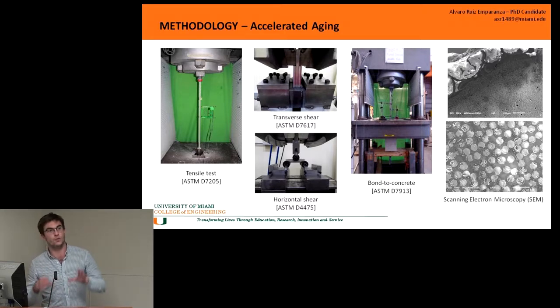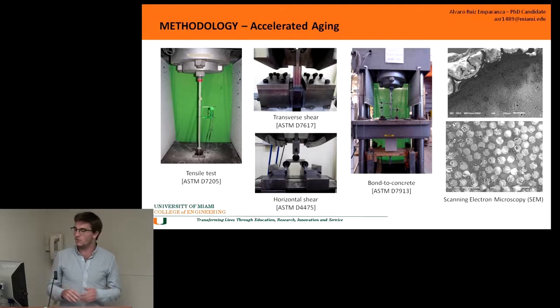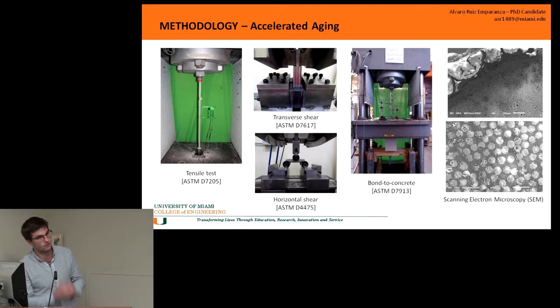So what we need is to check the properties before and after this accelerated degradation. We do a lot of testing. We do mechanical testing such as tensile tests, different shear tests, and also bond to concrete, since it's a very important parameter. And we also go a little bit more fancy. We go to the microstructure. We do SEM, which is scanning electron microscopy, and we check in the microstructure how that degradation is affecting the material, and if there is a big difference between the pristine material that comes directly from the manufacturer and the material that has aged.